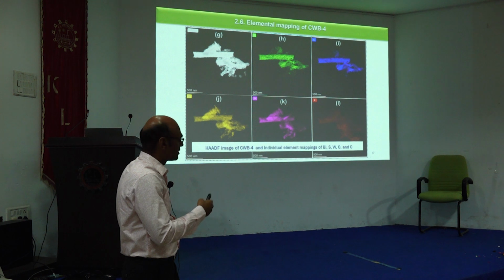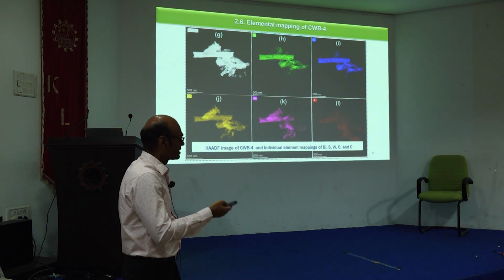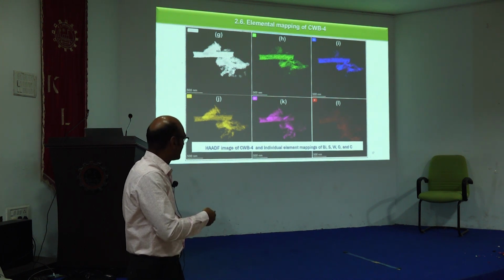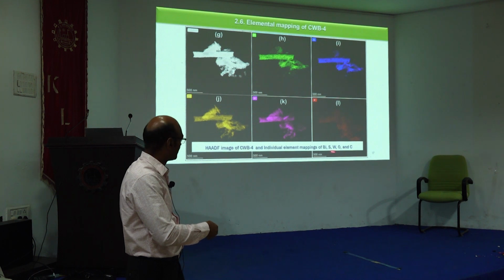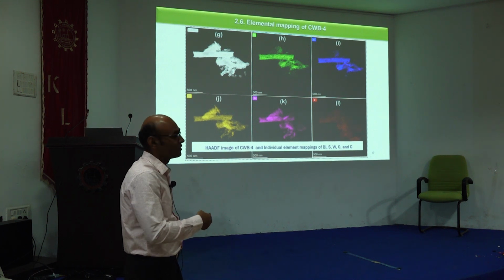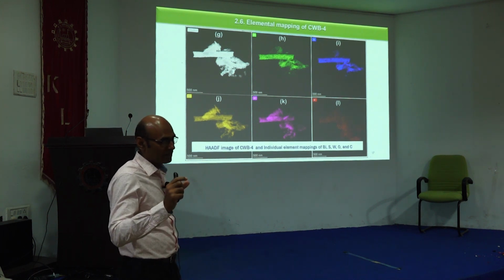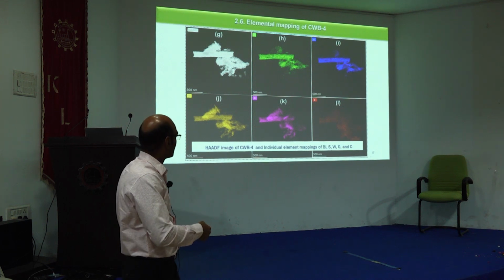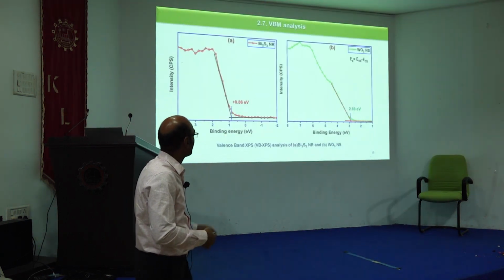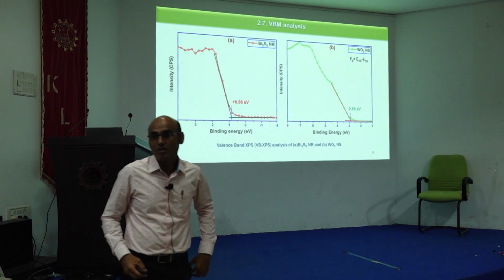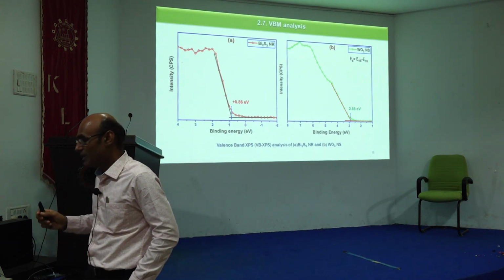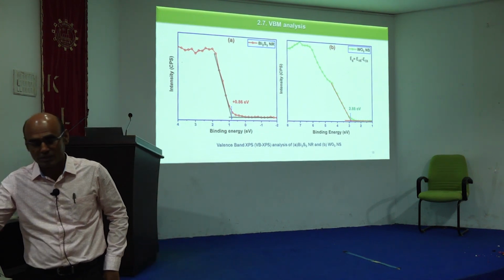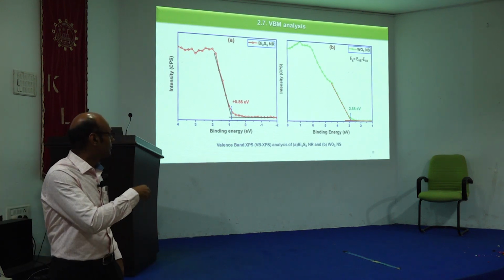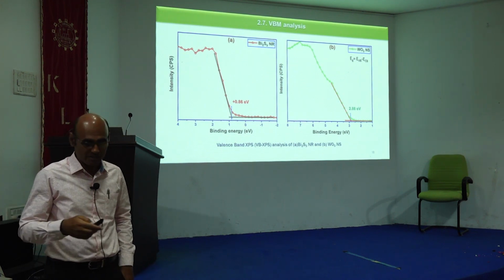We have bismuth, sulfur, tungsten, oxygen, carbon, everything we confirmed as we mentioned here. So we confirm the ratio, and we can also understand it in this elemental mapping. From the valence band spectra, we can also calculate the band gap or band potential of the given material. This way you can get very interesting information.